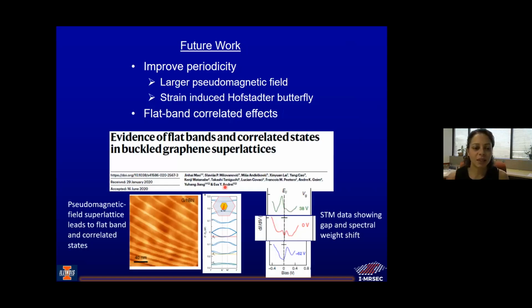Now, this is a paper that came out in June of this year. It's another scanning tunneling microscopy paper out of Eva Andrei's group. But what she did is she put graphene on a surface and saw these wrinkle structures that appeared. And these are sort of naturally occurring periodic wrinkle structures. And then their calculations showed that you expect to see not the standard, intertwined band structure that you'd get from many materials, but rather, around the Fermi energy, you get these regions of non-dispersing bands.